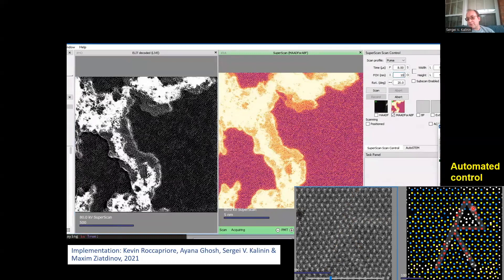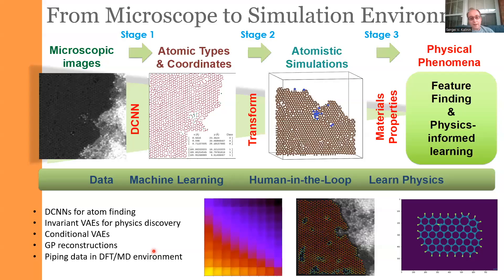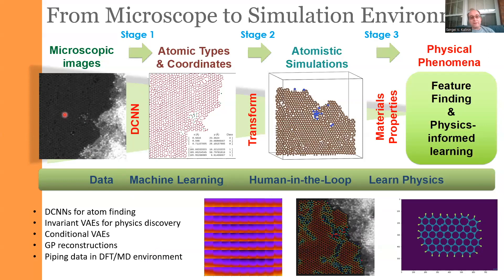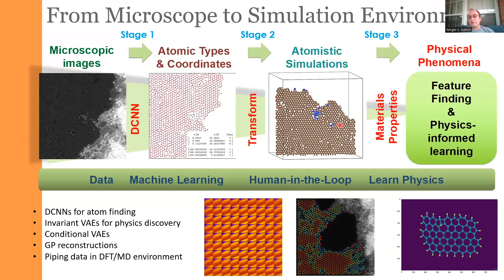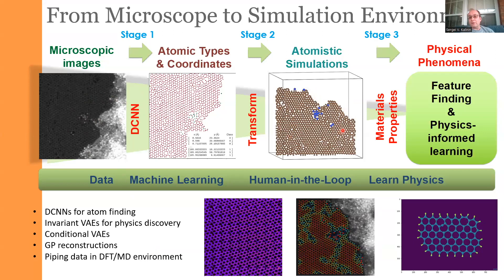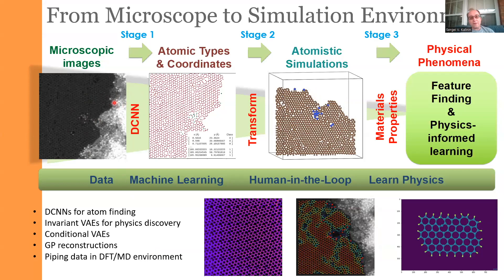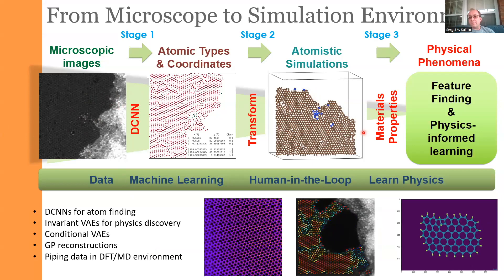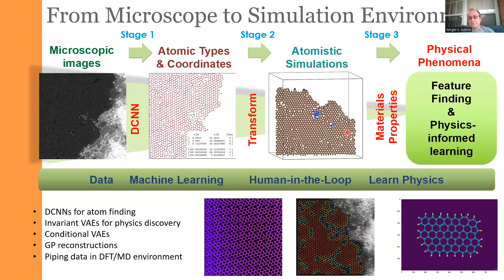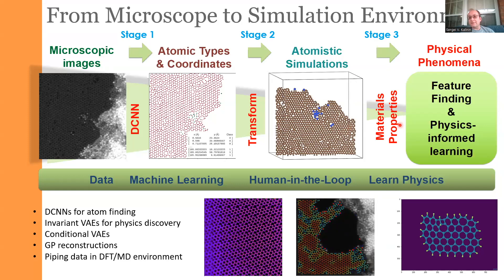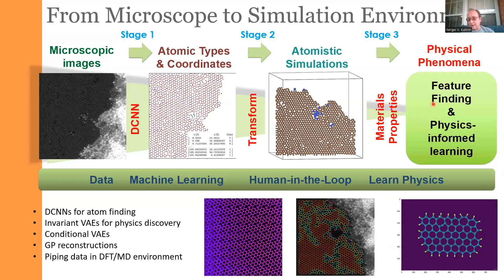It took us five years to learn how to solve this problem, and now it works. You can run the microscope where you acquire the image and the deep convolutional network converts the image to atomic coordinates in real time. Once you can do it in real time, you can run some pretty cool experiments — for example, you can tell the electron beam to follow a certain path and kick out the sulfur atoms, then visualize the resulting structure. It forms the letter R — we created an extended defect in molybdenum disulfide: essentially a letter written on the atomic level. We can also take data from the microscope, analyze it in real time, and send it into the simulation environment. In principle, if you have proper theoretical models, you can analyze data as fast as it is generated, though computationally DFT and MD computations are considerably slower than the microscope's data generation rate.